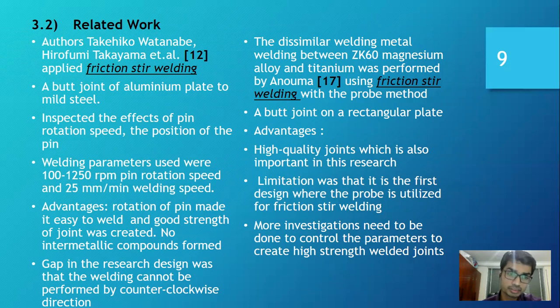The welding parameters that he used in his study were 100 to 1250 RPM pin rotation speed and 25 mm per minute welding speed. The advantages of this design were that the pin rotation speed was easy to control. So the welding parameters can be adjusted to create a good strength of welding joint, and there were no intermetallic compounds formed. However, one gap in this design was that the welding can only be performed in clockwise direction. It cannot be performed in a counterclockwise direction.